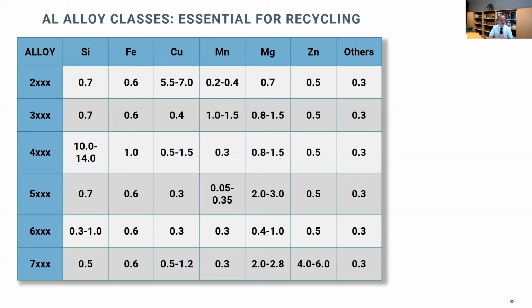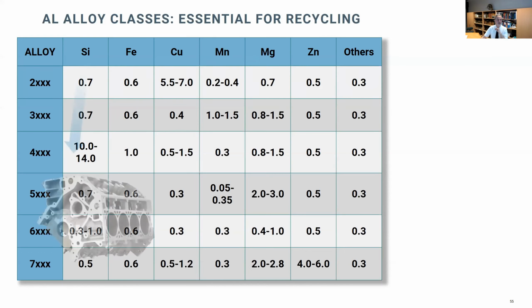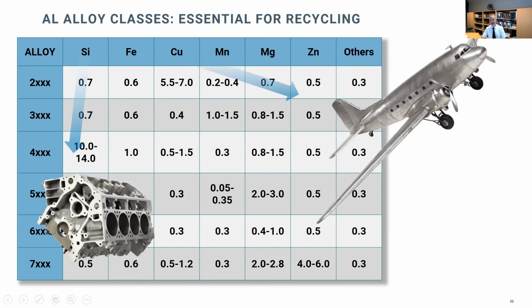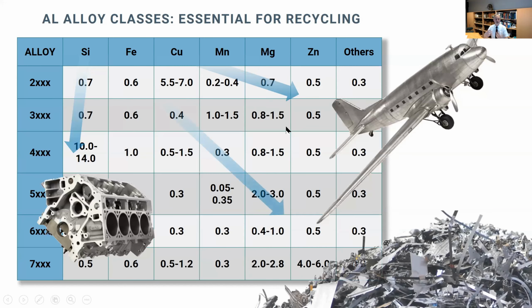One very important point about aluminum alloys to keep in mind is that they are very, very sensitive. That means you cannot easily mix them. And that is a real burden associated with aluminum. It's so nice to melt them, but when you mix them, you poison them mutually. So for instance, to give you a feeling, many cast products like huge engines and so on are very high in silicon. Or the alloys that you have when you fly in a plane that keep you safe are very high in copper content. Or the post-consumer mixed scrap, which is very important to retrieve but very hard to retrieve, is very, very high in iron, because it is mixed with iron scrap, connected to pieces of iron and so on, and gets iron content from the cutting of the pieces. And all these different alloy groups you can typically not readily mix.